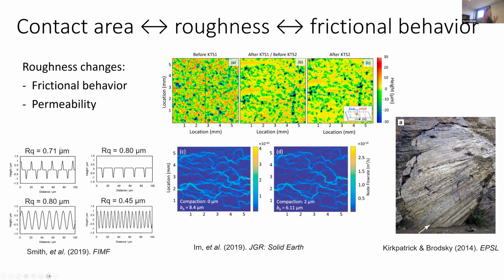So this has a lower RMS roughness coefficient, whereas here the mean roughness would sit slightly below the surface, and then all of a sudden almost all the points deviate from the mean. So even though I would call this surface smoother, it has a higher RMS roughness coefficient. And this top right and this bottom left actually have the same RMS roughness value. But if you would model the contact area of these two surfaces, this surface would probably have much larger contact asperities. So RMS roughness in itself is a measurement that's used a lot, but it doesn't capture all the behavior of a surface.